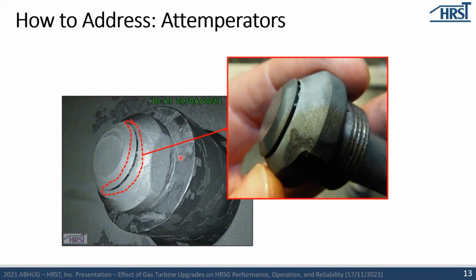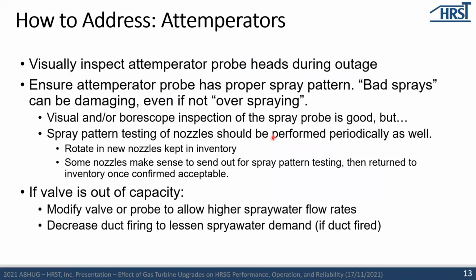This is an example from a recent inspection showing that the spray water probe valve head is actually stuck open due to debris in the system. So this was actually leaking water into the system even when there was no spray water demand. And if your valve does run out of capacity, you can look at modifying the valve and the probe for higher spray water rates, or potentially decreasing the amount of duct firing that you have in your HRSG to lessen that spray water demand if you're duct fired.